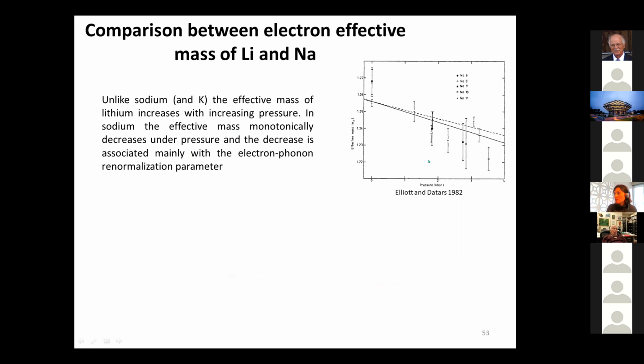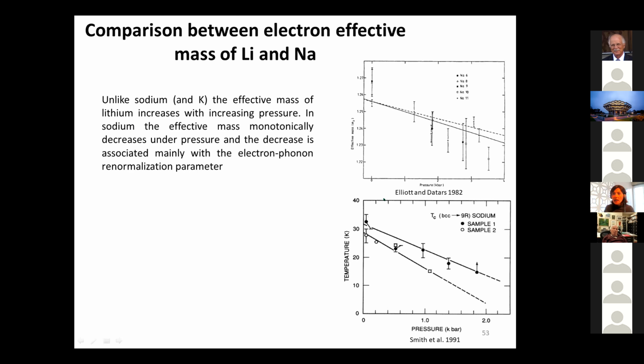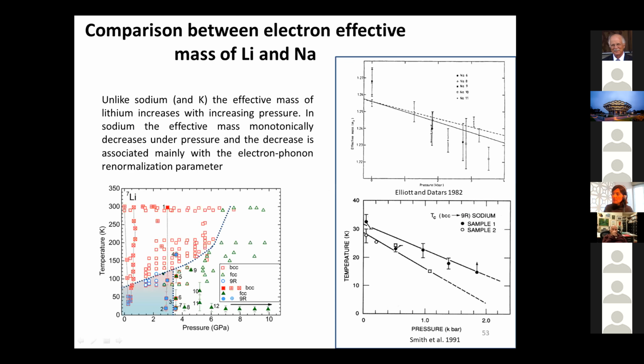How can we explain this? Lithium does what we would supposedly expect, because as you go to higher pressures, you assume the lattice starts interacting more efficiently with the electrons, and therefore the electrons become less free-electron-like. But in sodium there is the opposite effect, and similarly this has been observed in potassium. One way to think about it is that sodium also has a martensitic transition, but in contrast to lithium, where the martensitic transition is enhanced under pressure, in sodium it goes down and dies off under pressure. What we are thinking is that the presence of this disordered phase could lead lithium to show less free electron behavior as we go to higher pressure.